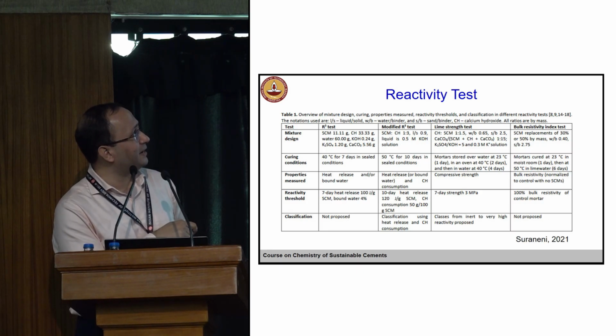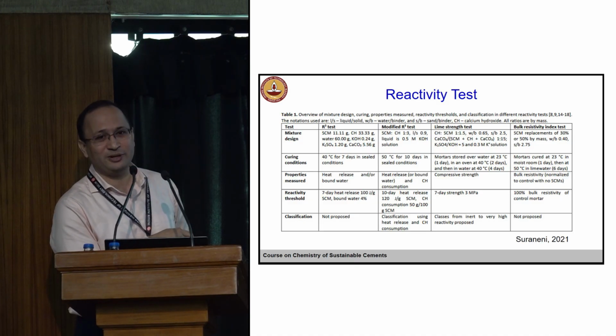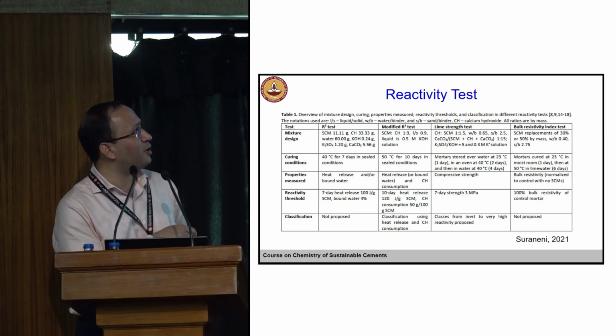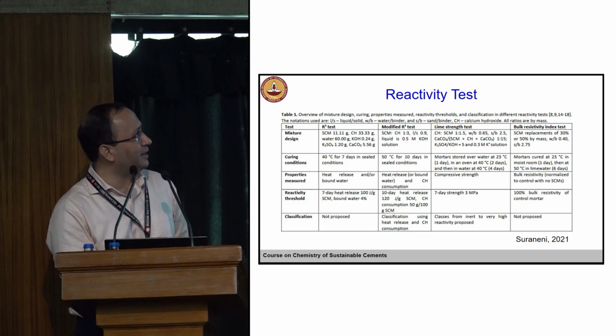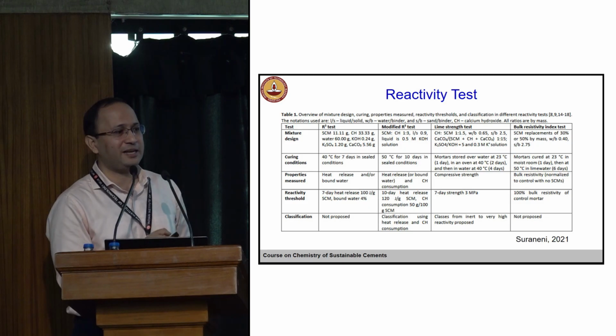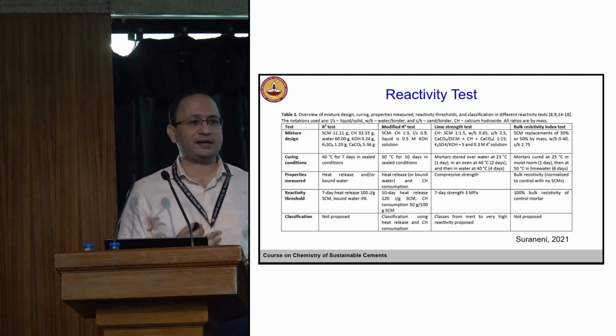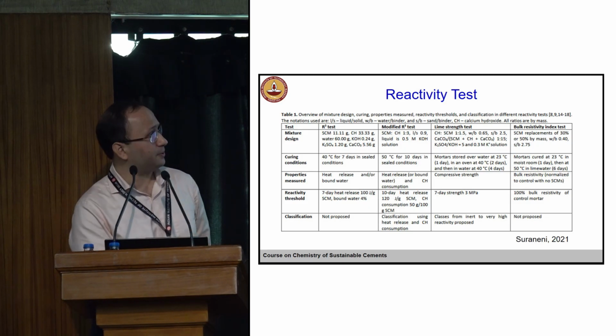Essentially, in R3, you are mixing SCM with calcium hydroxide, in the presence of sulfates and carbonates. That's the environment you simulate. And then you cure it for a certain time, you monitor the heat release and bound water, right? And then examine its reactivity. Modified R3 slightly changes, the temperature is increased. It's specifically for the slowly reactive SCMs.